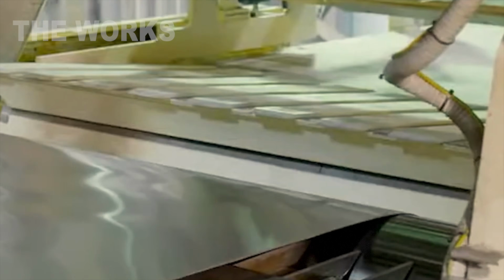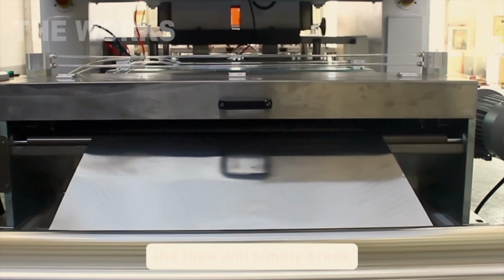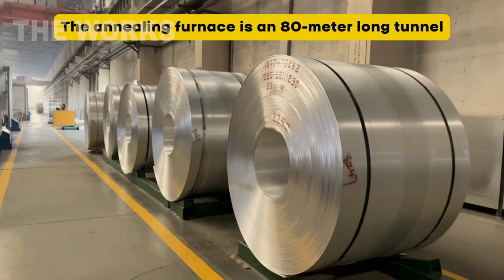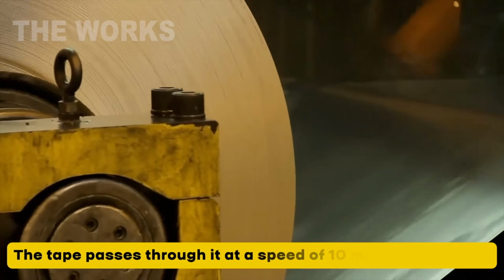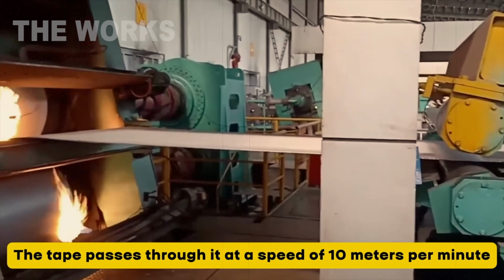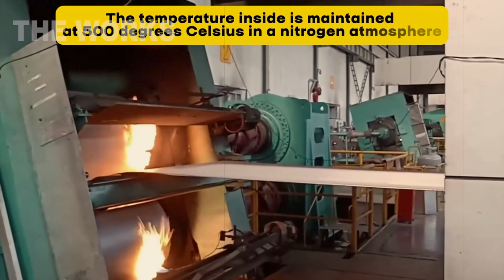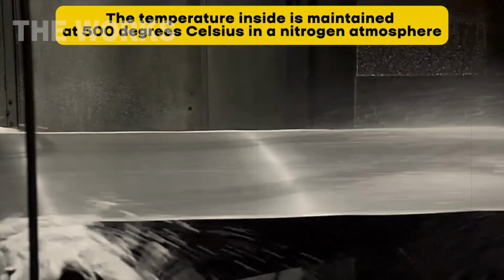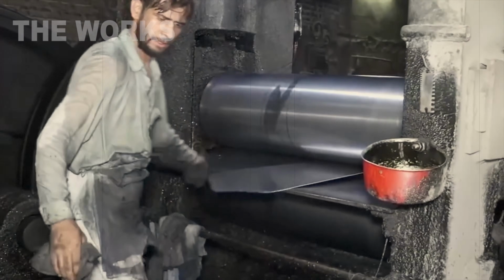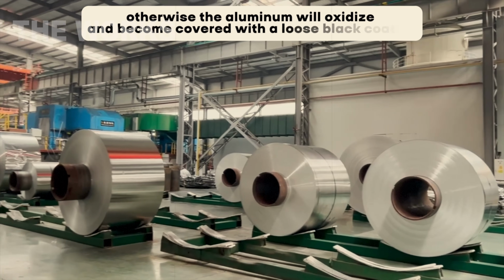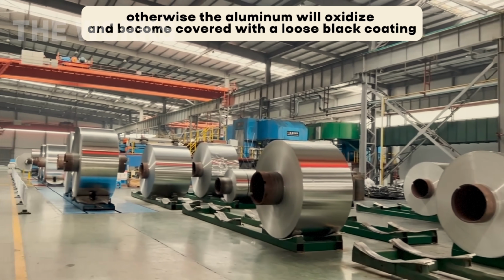...the strip just tears. The annealing furnace is a tunnel 260 feet long. The strip travels through at 33 feet per minute. Inside, the temperature hits 930 degrees Fahrenheit in a nitrogen atmosphere. Oxygen is completely excluded. Otherwise, the aluminum oxidizes and gets covered in loose black scale.